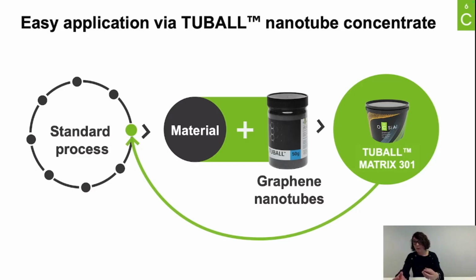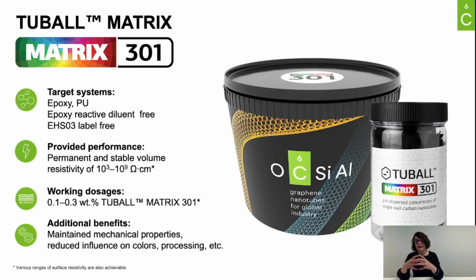So in the example that we are reviewing today, ESD floorings, to design a PU-based or an epoxy-based 100% solid floor, our customers will be using our grade TUBALL Matrix 301. TUBALL Matrix 301 is 100% compatible with solid systems, epoxy, and PU. And a very important point to know about this grade is that it's 100% epoxy reactive diluent free. So no EHS03 labeling. Typically, the resistivity performances that we can provide with the TUBALL Matrix 301 range from 10^3 to 10^9 ohm-centimeter.